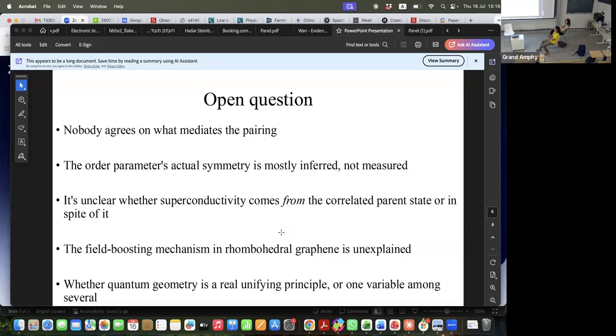And still, people do measure tunneling, either from STM, which is still a small tip but still screens, or from a neighboring tri-layer, which they probably have some argument why it screens less, but I'm not sure what the argument is. The STM here is a problem because you need to have both gates in order to go to any of the superconductors, because they are at finite D field. So it's not simple. But you can change the thickness of the hBN. You can do this, but the STM cannot sense that. It needs an open surface, right? The only thing is the SQUID. That's why I was telling you that these papers on domains and stuff use a SQUID scan.